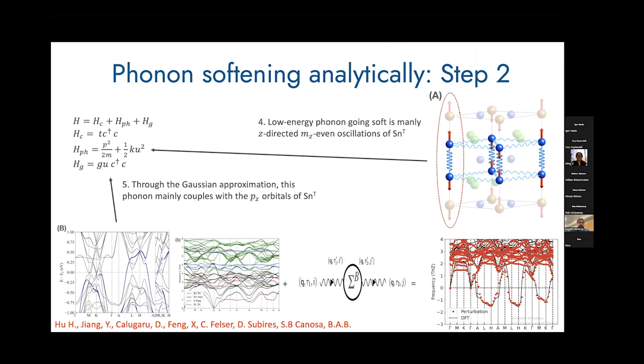And what you can do with this electron-phonon coupling, which is very, very easy, is that it neglects all the other electron-phonon couplings. So for example, it is not going to give you a good spectrum for the higher bands, but it should give you a good electron-phonon coupling between this phonon, the soft one, and the electrons present in the tin.